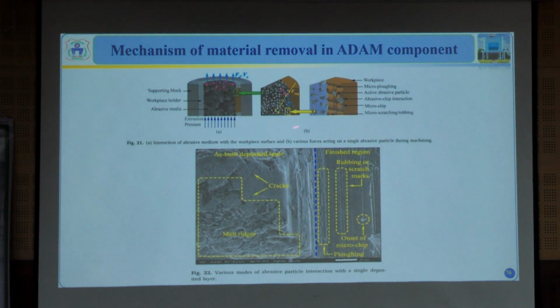And the mechanism you can see here. The abrasive particles travel over the work surface, and schematically, whatever the observation in the SEM image, it explains what kind of machining takes place, like rubbing action, micro plowing action, and the shearing action of the abrasives. All this we need proof for, right? So the mechanism is explained with the help of SEM images. This is a possible rubbing action, this is a possible finishing region, and this is as built.